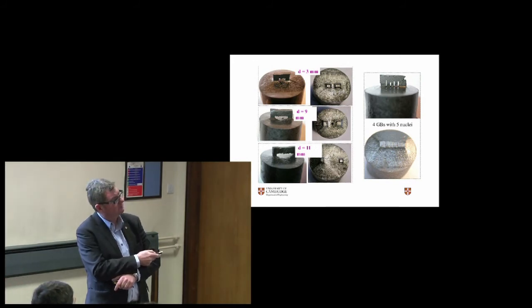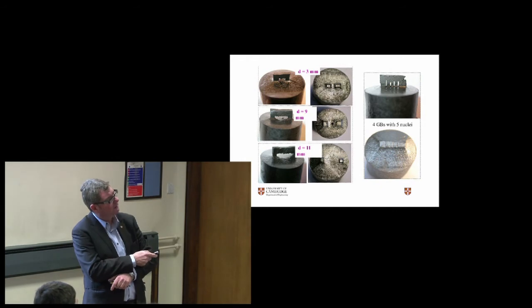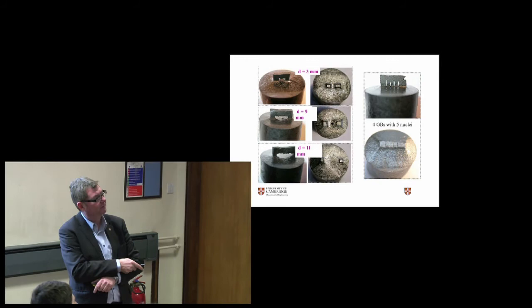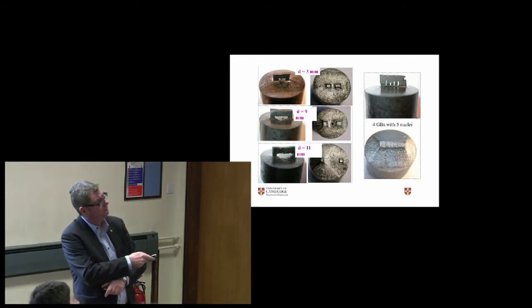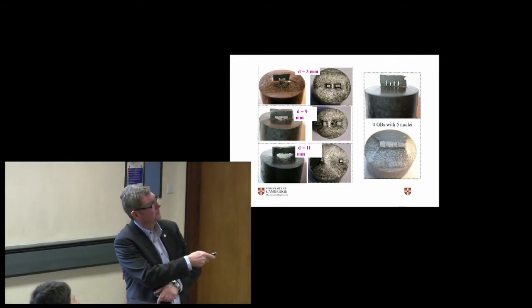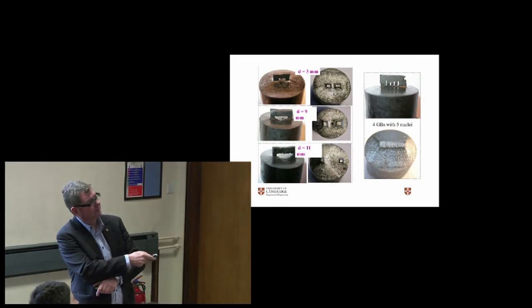So this is a doubly seeded material. Here's our doubly seeded sample with the seed removed. So there's a grain boundary down the middle. And we can increase the separation of the two legs, so you can see the separation is getting further and further apart. We can go to more than one nucleation site. So here we've got 5 nucleation sites. When we remove the grain with the seed, we see this site. You can see the facet lines here as well.